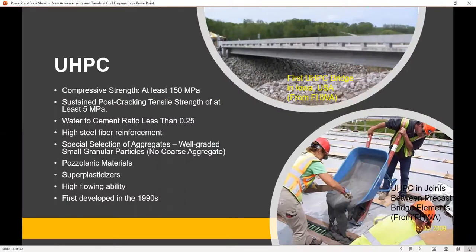Now let's talk a little bit about ultra high performance concrete. There are different definitions for it, but the Federal Highway Administration in the US defines UHPC as concrete at least 150 MPa in compressive strength. Now, it also has to have high tensile strength, but also, if you get to a tensile strength limit, we don't want the strength to drop to zero. We want it to sustain itself. So after cracking, it should still hold a 5 MPa tensile capacity. That means it will give concrete a more ductile behavior. Normal concrete, when it gets to a cracking load, suddenly drops to zero, and that's its very brittle nature.